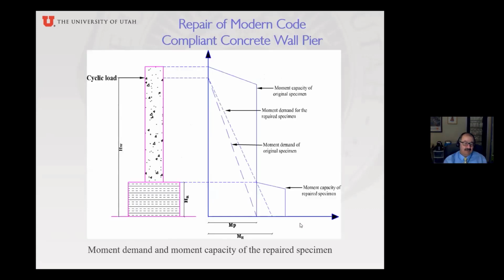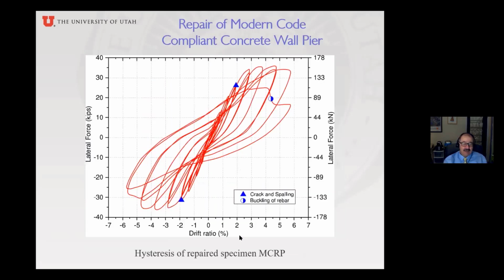So you have to be careful when you do this, because the original moment demand was down here. But now that you put this donut, your demand, of course, increases. So you have to be careful when you do retrofits like this to protect the wall so you don't exceed the capacity. So here's the performance of the hysteresis of the repair. You can see the repair is pretty large, and it went all the way to 6%. So definitely satisfies the code, even the current code, even the Caltrans code.